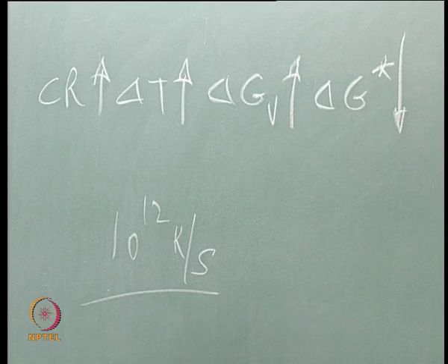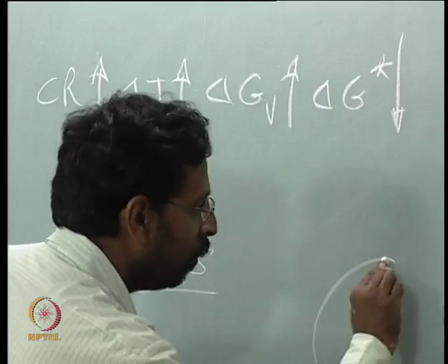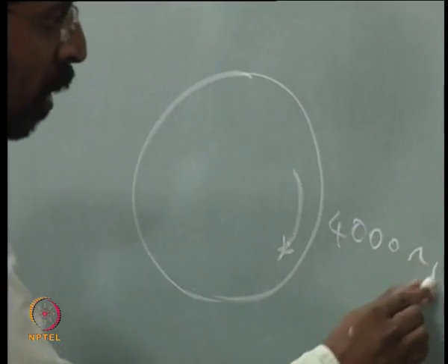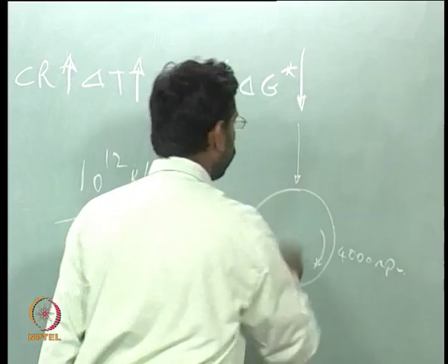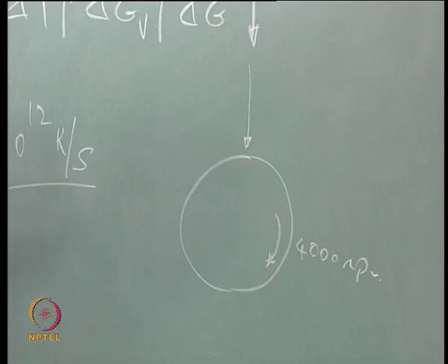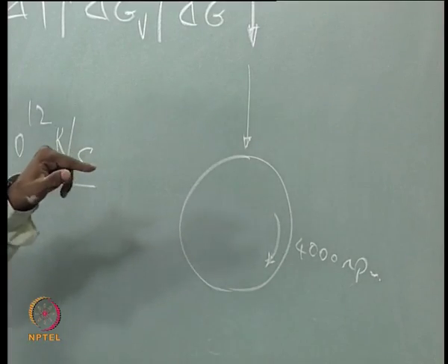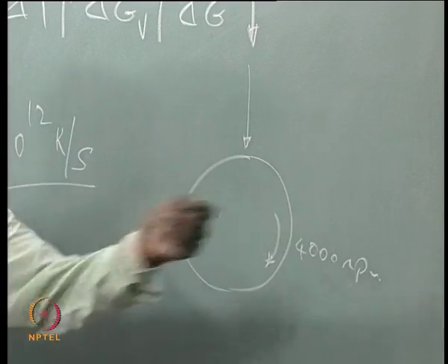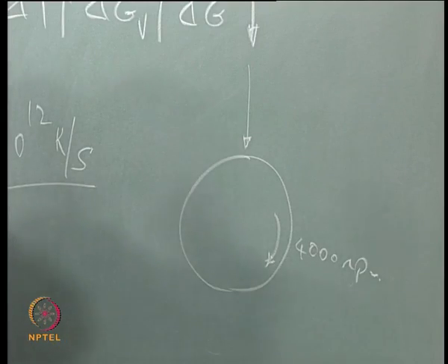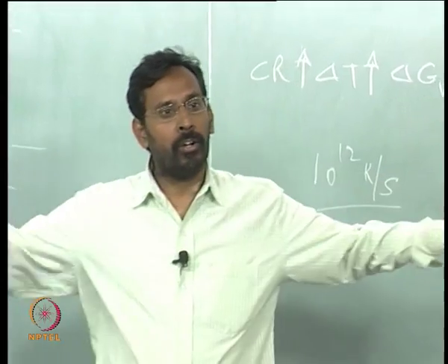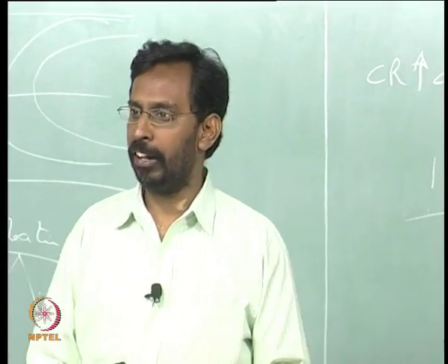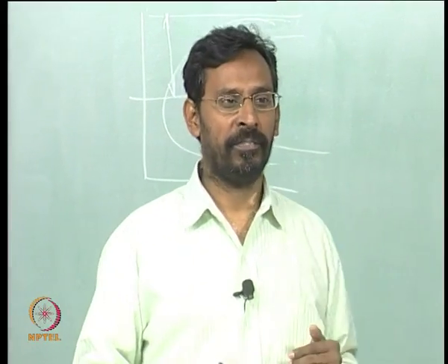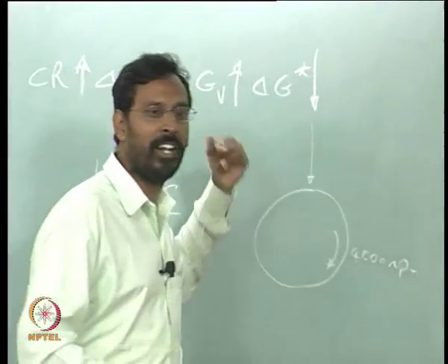That is what I said, melt spinning is the one where we talked about it, where you take a wheel which rotates at a certain speed like 3000, 4000 rpm, and you pour the liquid metal on this. The moment a droplet falls, because the wheel is spinning, it pulls this droplet along with the wheel. So the droplet sticks to the wheel and then gets pulled. As a result, the droplet gets converted into a sheet of metal. It is like rolling without a second roll there. So you get flakes, every droplet becomes a flake.